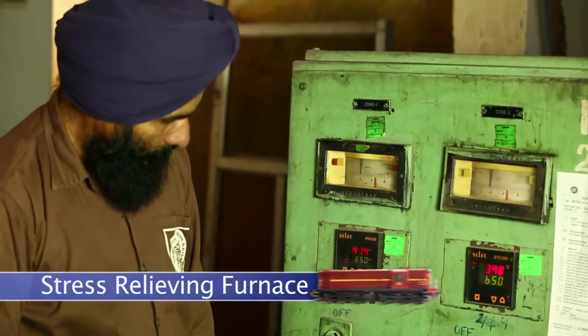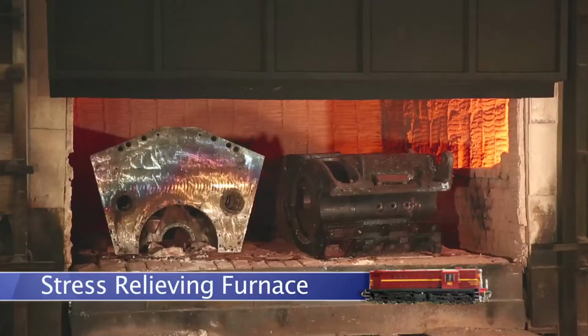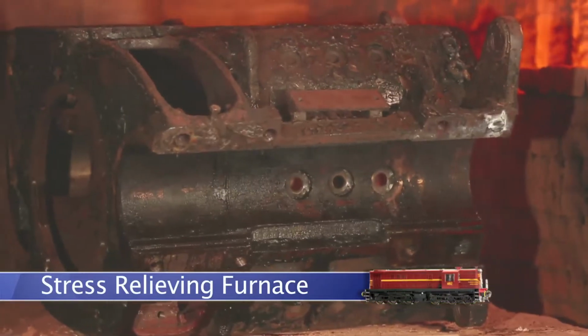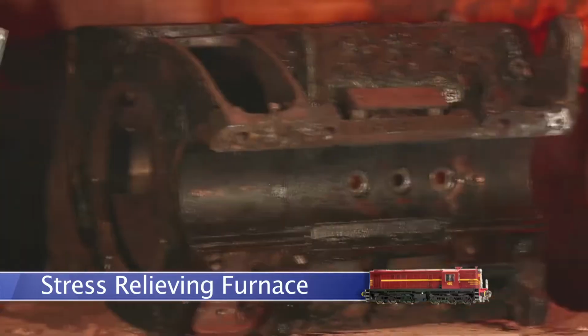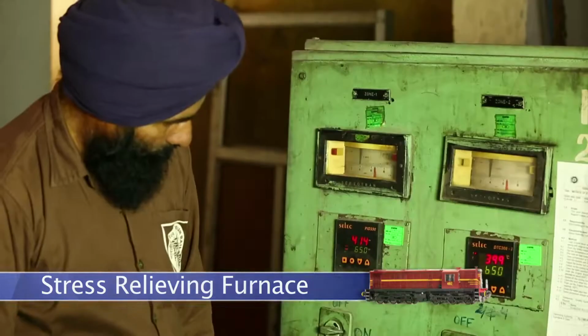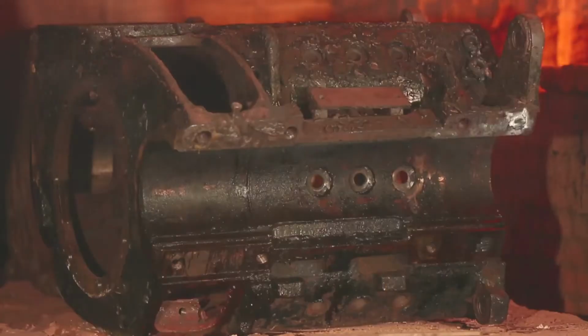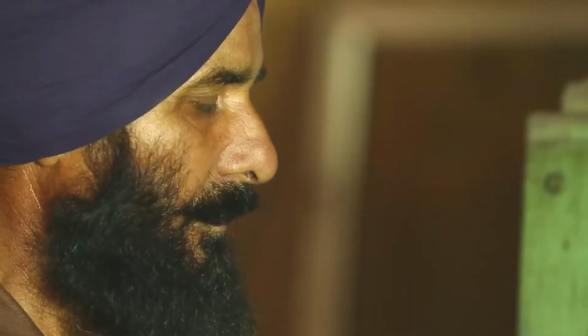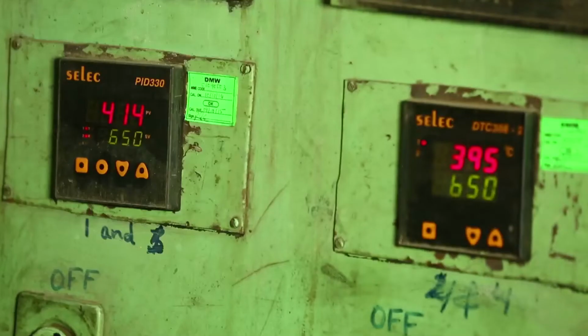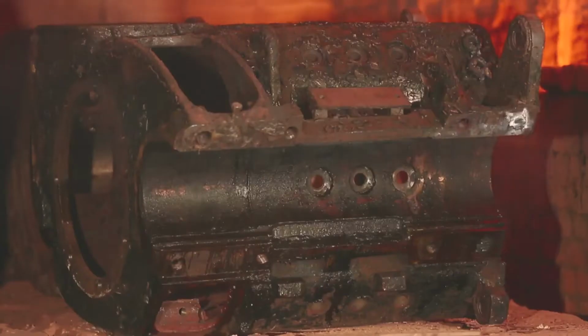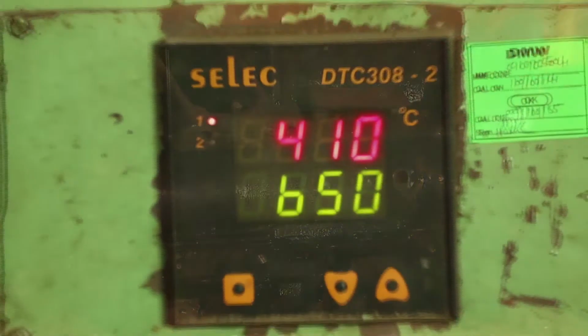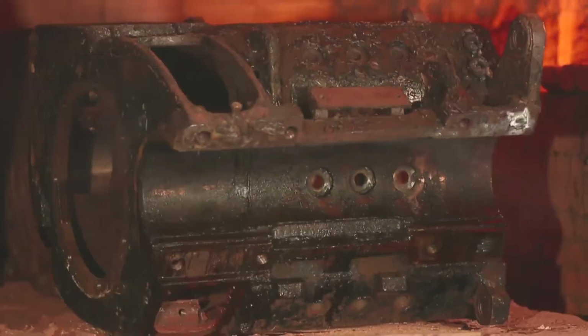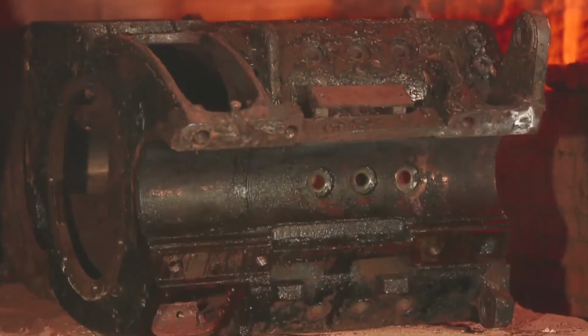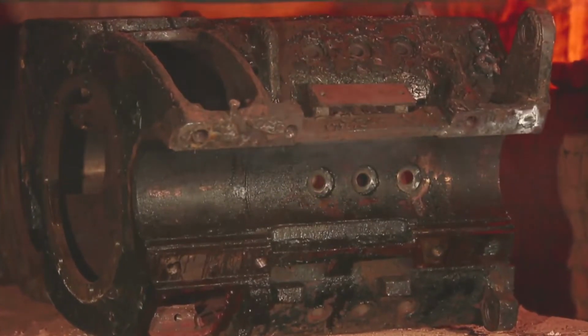The stress relieving furnace is used to relieve internal stresses of magnet frames and engine blocks which develop during welding. It also increases machinability of components. The components are heated at the rate of 70 to 80 degrees centigrade per hour up to 650 degrees centigrade and held at that temperature for soaking period of 4 hours.